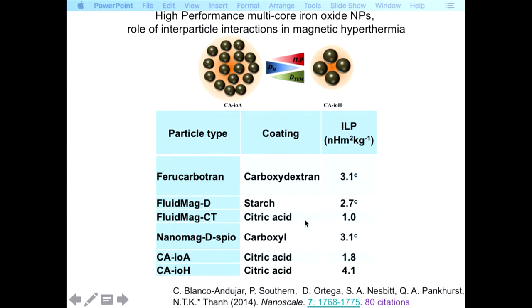So fundamentally, it's very important when you make the nanoparticle that you say what nanoparticle will make 10, 15 nanometer? But now it is much more sophisticated because they aggregate together or form clusters. You can see already the effect of the gold nanoparticle that changes the color, but also the magnetic effect. You have a magnetic anisotropy and also the magnetic dipole-dipole interaction. So the interaction within the particles will give you different heating efficiency.